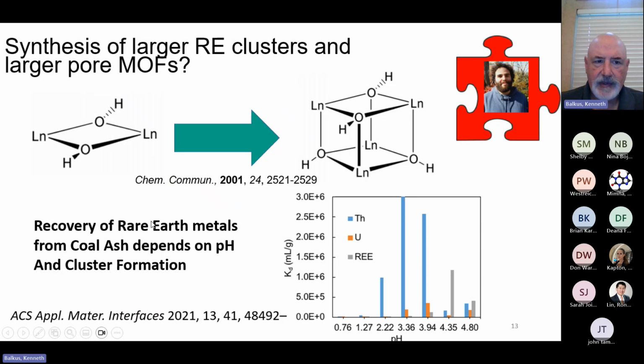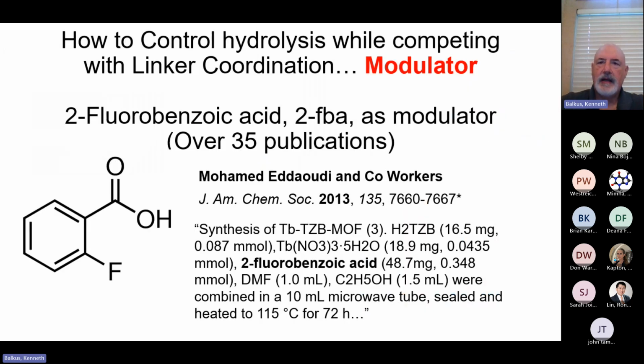And this was based on the fact that we were using some of our carbons to remove rare earth ions from coal ash. Part of the reason why these were so selective is that, depending upon the pH, one gets different cluster sizes. So we thought, gee, maybe if we can control that, we can make bigger pore structures. And so Juan went to the literature and found that people indeed had made some bigger clusters of rare earth ions, and they used a modulator.